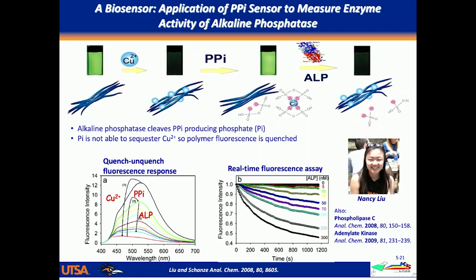So in this case, what you do is you take the polymer, it's fluorescent, you add copper to it, it's turned off, then you add pyrophosphate and it's turned on. But in this system, you have the three components present. You've got the copper that's sequestered with the pyrophosphate, and you've got the polyelectrolyte, which is fluorescent. But now if you add the enzyme to it, the enzyme begins to catalyze the hydrolysis, and the copper goes back to the polymer, and the fluorescence turns off.